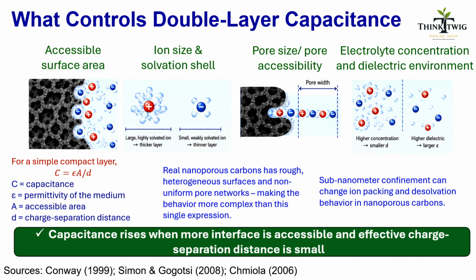So, what actually controls double layer capacitance? The first important factor is accessible surface area. A carbon material may have a very large total surface area, but only the surface that ions can actually reach can form an effective double layer. So the total area and usable area are not always the same. The second factor is ion size. In a liquid electrolyte, an ion is usually surrounded by solvent molecules. This surrounding layer is called the solvation shell, and because of this shell, the effective size of the ion can be larger than the bare ion itself. That affects how closely the ion charge can approach the electrode.